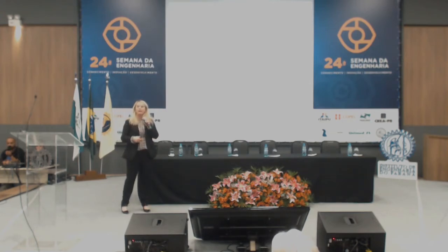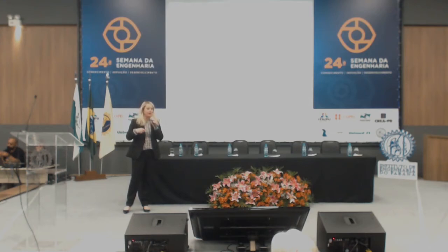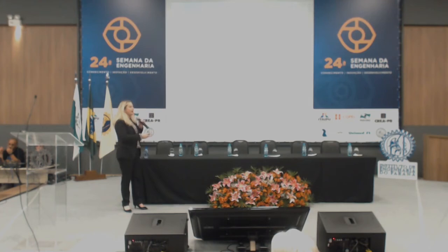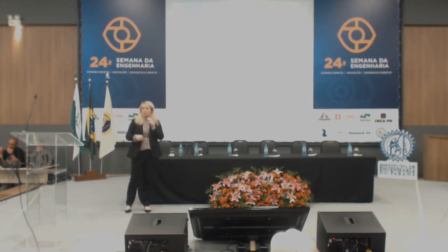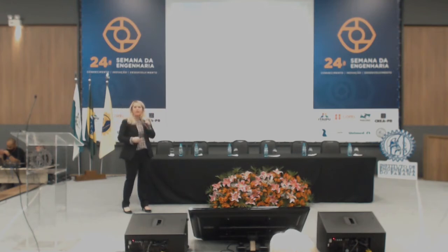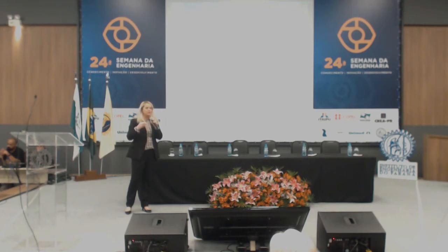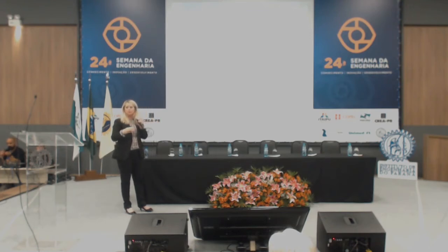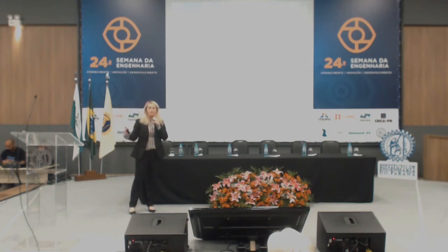Another example is repair of post-tensioning structures. So this is a post-tension structure in Alabama that had voids in the grout of the post-tensioning. And so you can see where those voids were, there was heavy corrosion. And so a new grout was injected inside of the duct, and the new grout contained the amine-based corrosion inhibitor. The amine-based corrosion inhibitor has been able to reduce the rate of corrosion and has been in place since 2003. So we are now 15 years out and reducing the corrosion on this bridge.